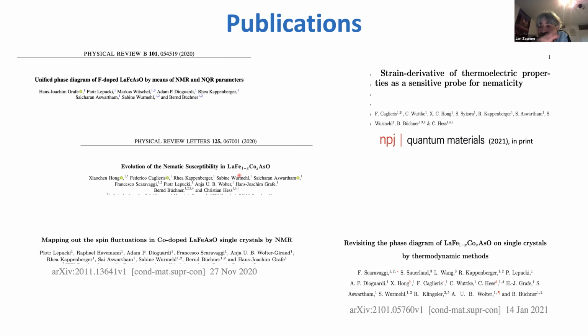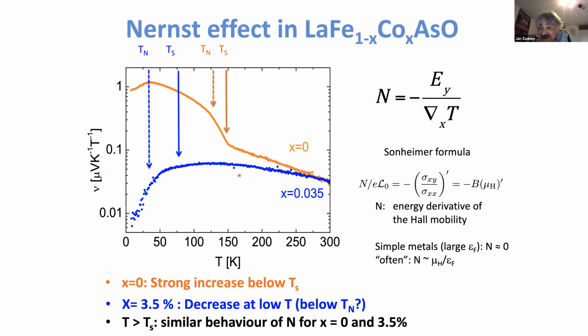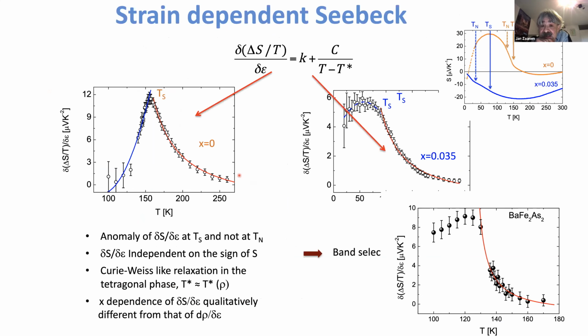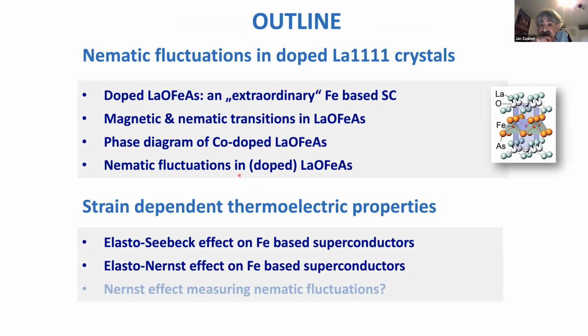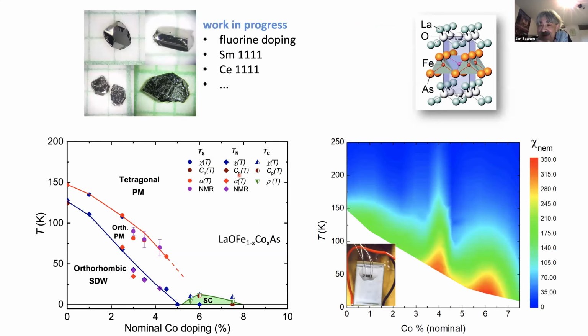Right, so could it be that this disconnect between the neat and orderly behavior of the nematic susceptibility, contrasted with the very disorderly behavior of the orthorhombic transition, is just about this transition turning into a first order transition when the lattice starts to feel the nematic susceptibility? And then you can have this sort of Imry-Ma type of physics, right? The first order transition plus disorder gives you puddling that is smearing out a transition. Could that be? Is this a thought that other people have had?